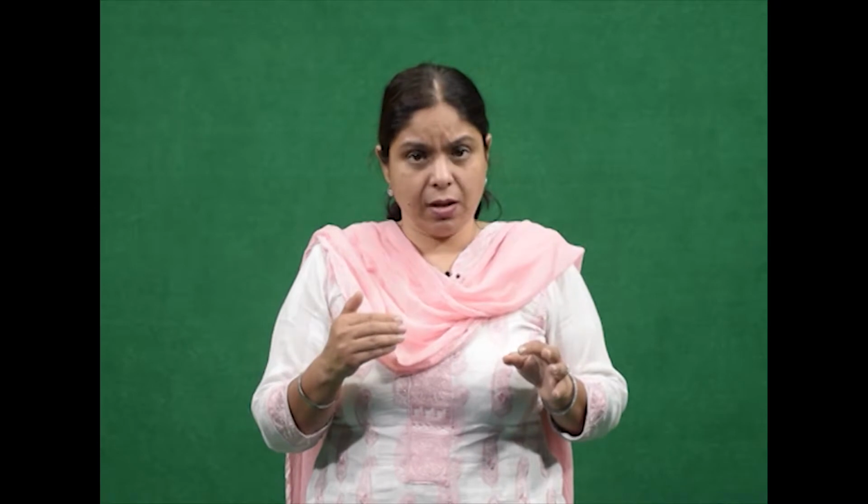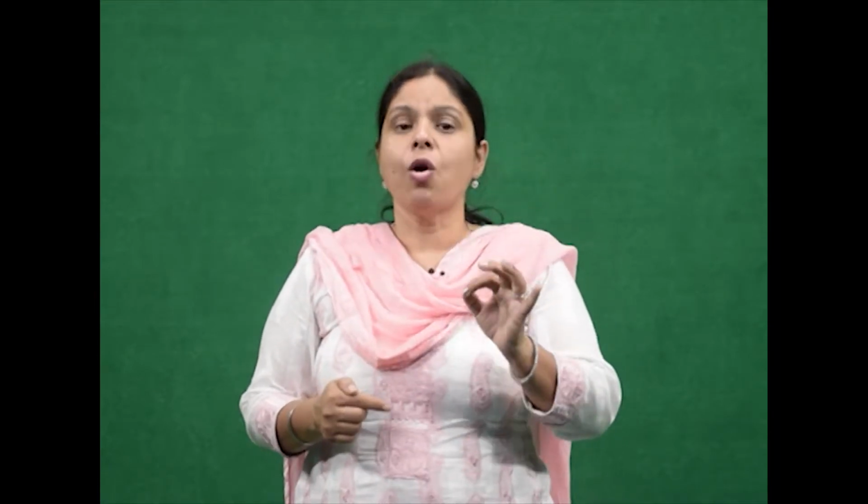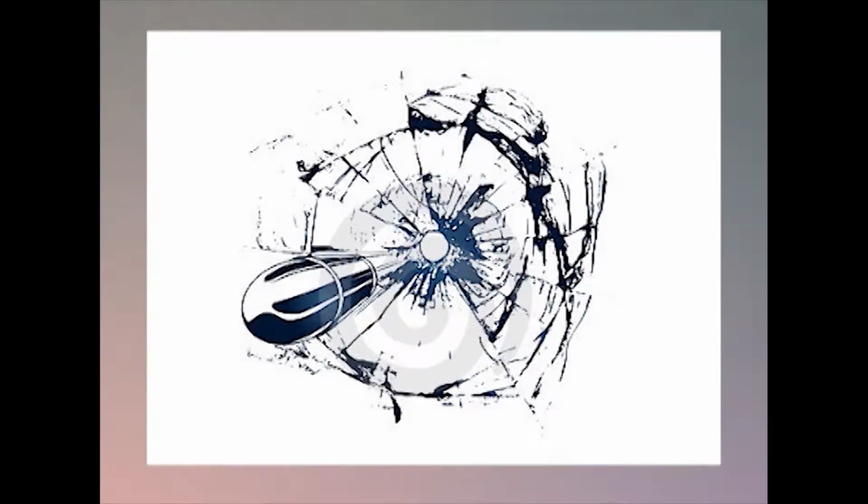If a projectile approaches in a perpendicular fashion, the crater is symmetrical. In the case of a very high velocity projectile, such as a rifle bullet, it will yield a small hole with minimum flaking around the circumference. A slow moving bullet, however, delivers a more irregular hole with substantially more flaking.